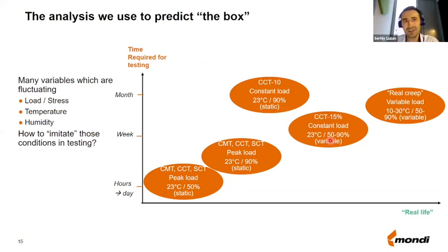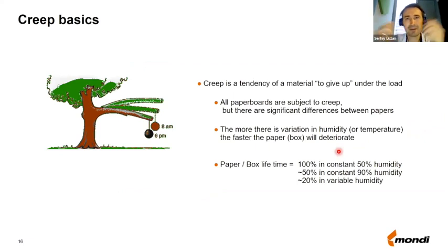Of course, in ideal conditions, you would like a test where you don't only change the relative humidity, but you also change the temperature, and ideally you can also change the load. But this test does not yet exist. So for now, the best test which can mimic real life conditions is this CCT 15% test, where you can subject the paper to a constant load and change the relative humidity conditions and see how long the box or the paper will survive. And how long the paper will survive will depend on how good the paper's creep property is.